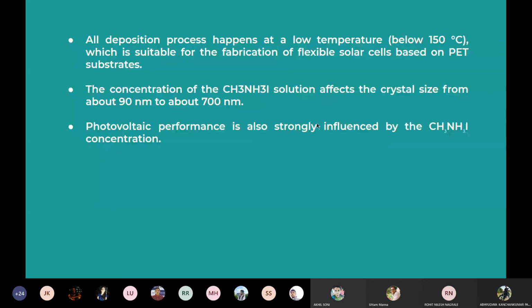And all deposition processes happen at a low temperature below 150 degrees centigrade, which is suitable for fabrication of flexible solar cells based on PET substrate. PET substrate is just polyethylene terephthalate, which is a derivative of ethylene glycol and terephthalic acid. The concentration of methyl ammonium iodide solution affects the crystal size from about 90 nanometers to about 700 nanometers. Photovoltaic performance is also strongly influenced by methyl ammonium iodide concentration.